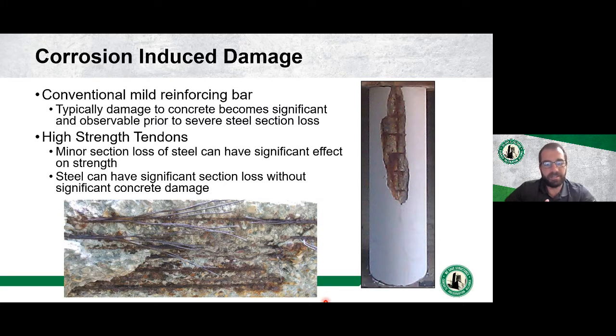By the time enough iron oxide was formed to create a spall, we have very significant section loss of the steel, complete breaks of those strands, and clearly we now have a structural issue with that element, as opposed to with conventional steel. If we're waiting for the same visual indicators to identify when we need to address a pre-stress or post-tension element as we would a conventional bar, then we're probably waiting too long. With those elements, we probably need to do evaluation and mitigation much sooner in their visual condition than we would with a conventional rebar.